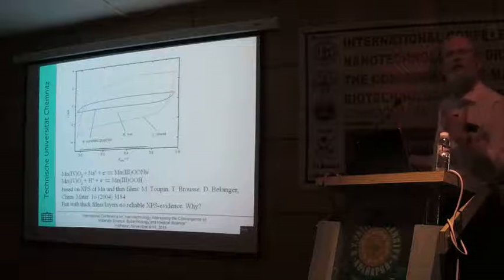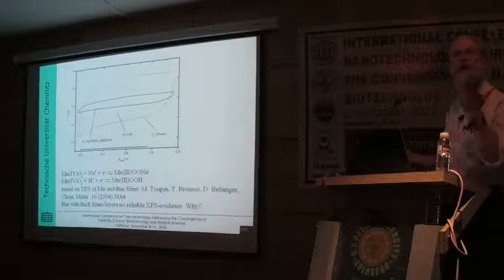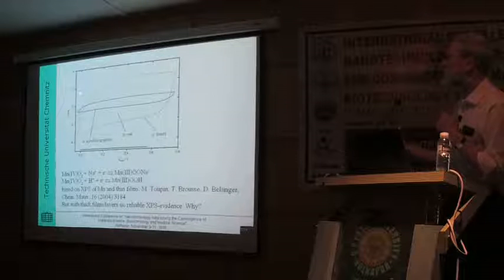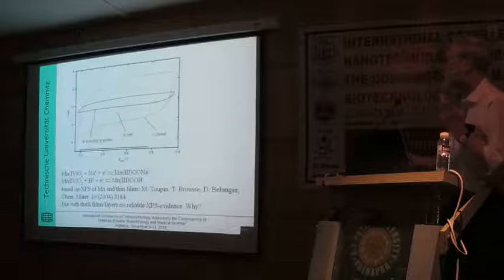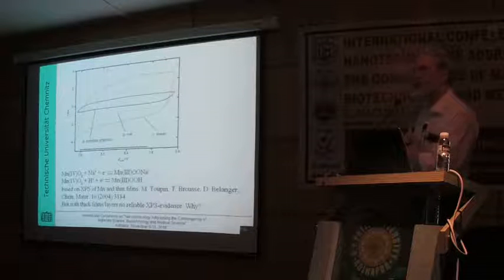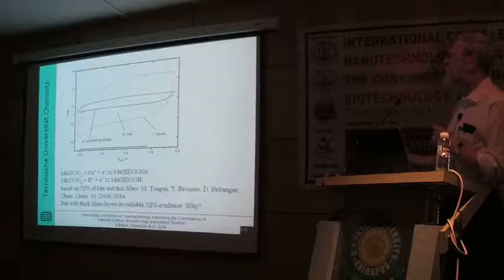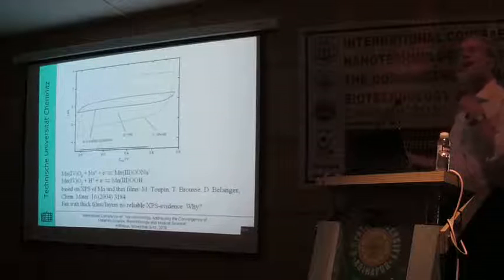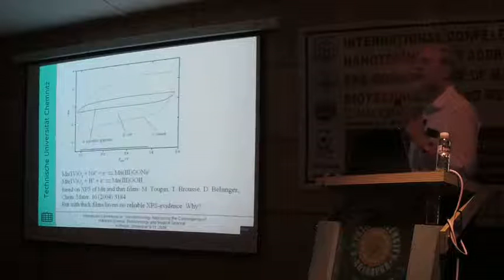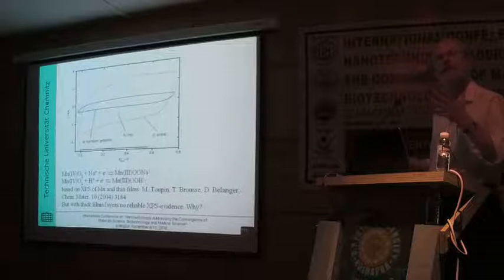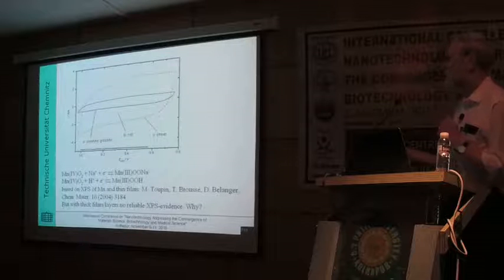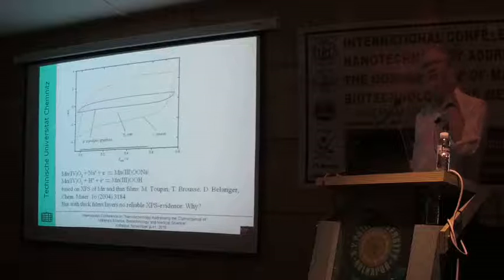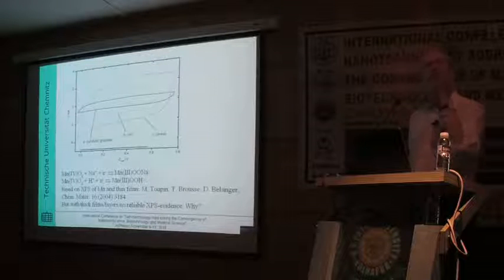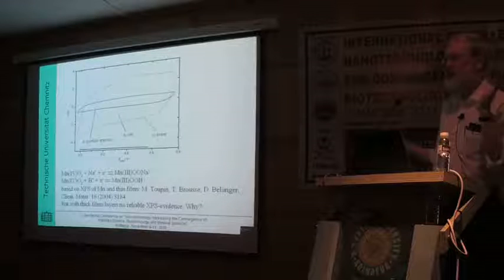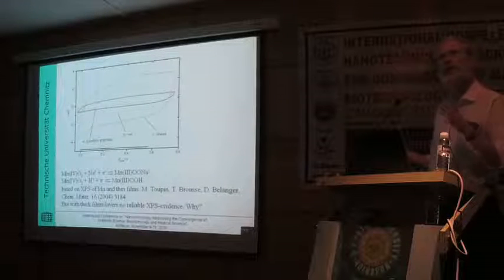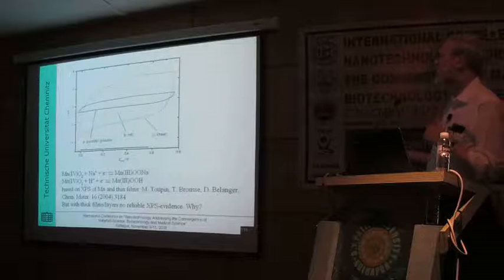Well, in case of the manganese dioxide, basically the same argument has been proposed. I already mentioned in passing. We are oxidizing the manganese 3 into the manganese 4, and what is going on for charge compensation? Well, first of all, we have the anions from the electrolyte solution, and also authors have claimed, well, the sodium ions are moving in for charge compensation, so some people talk about supercapacitive behavior of electrode materials in terms of ion absorption. But why is the oxidation of the manganese 3 into manganese 4, or of ruthenium, I don't know, 4 into 5, whatever the number we have picked, why is this response not showing up as a current peak, but in this particular shape?